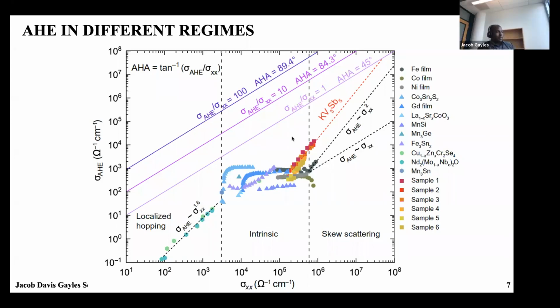Yeah, but also, the way we're calculating this broadening is not very realistic. So this broadening takes everything into account. I mean, it's just smearing the bands. But when you calculate the Berry curvature, you don't need broadening, really. You just assume it small because it doesn't depend on it in that limit. Yes, but you do need some amount of broadening. If you make it 0, then in some cases you get an ill-defined answer, right?